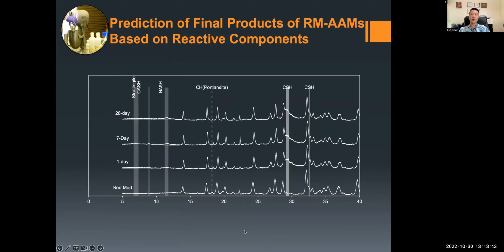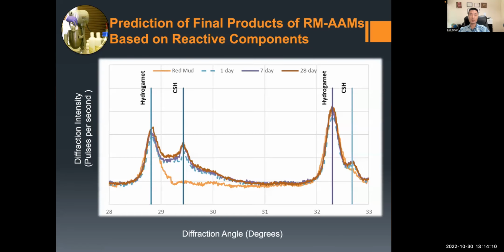The predicted final product will also be verified by XRD. In this example, we show the XRD of the raw material and concrete at 1 day, 7 days, and 28 days. By comparing these peaks, we see mostly the hydration product is CSH. We could also have some small amount of NASH. So this mix generates CSH mostly, as we can see from the peak here, a big change in CSH.